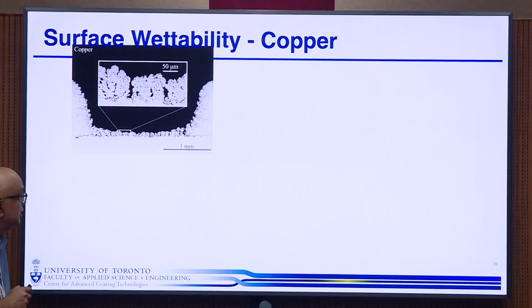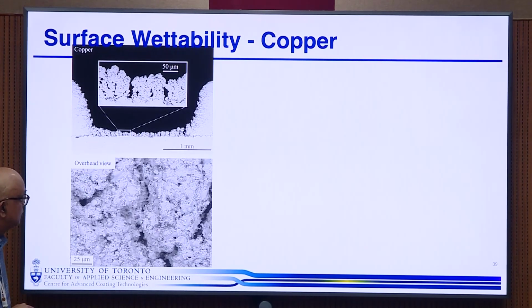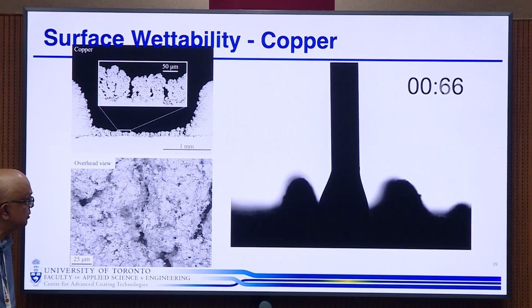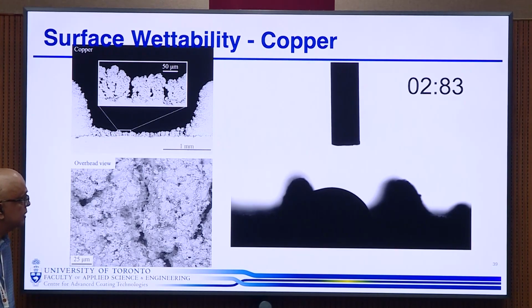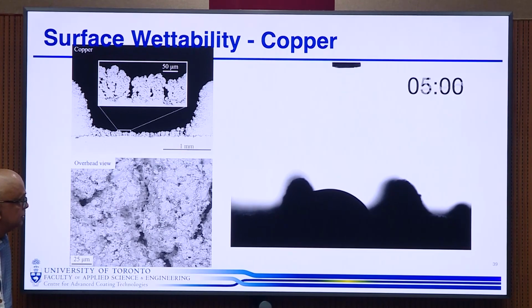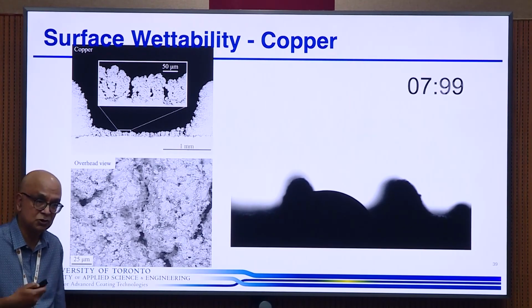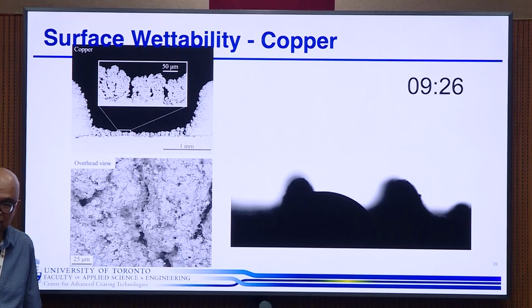The copper is not so much. So this is what the copper looks like, and you put a droplet on it, and it can take quite a while to soak in. And this is because of the oxidation of the copper, which makes it more hydrophobic.